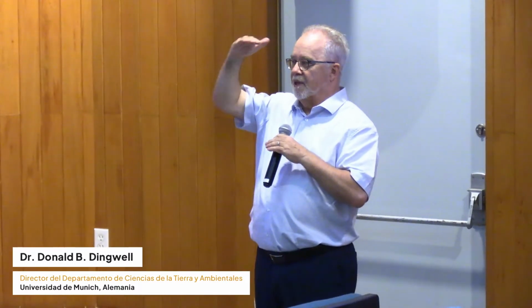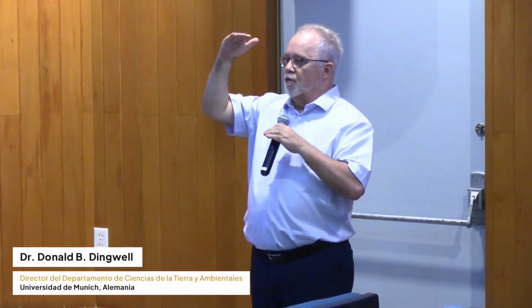Up to now, we've just been thinking about eruption A, eruption B, eruption C. We know the chemistry of the glass. We think we can estimate the fragmentation depth. That's always a big question, of course, because it's the fragmentation depth, meaning the depth from the decompression that takes place at the crater, which will give you the transit length and therefore the transit time before the system drastically cools and then it's just shut off.